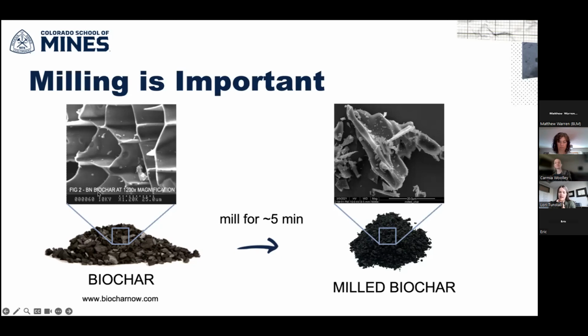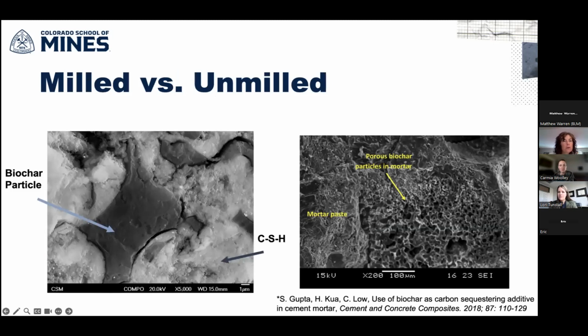If you don't do that, you end up retaining a lot of these pores in the cementitious mix. You can see on the right side all of the pores retained in a biochar that's not milled. And this doesn't work as well, right? Because air isn't contributing anything to strength, so you're going to see strength decreases. That's really important, and it does account for some of the differences that we see in our group compared to other researchers. But it's certainly not the only difference. We've tried to copy what some of the other groups do in terms of their processes, and that's just one factor. We're still trying to understand the rest of the factors.